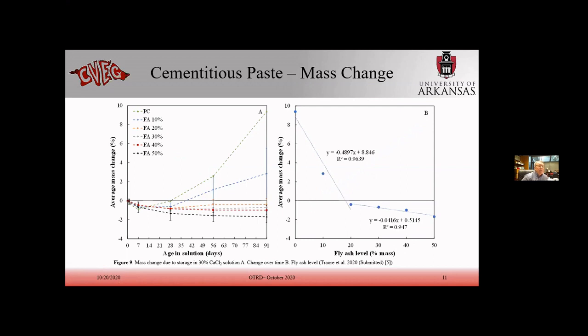Likewise, mass change. We looked at the change in mass after the 91 days in the calcium chloride solution, and this is a gain. As you store the cubes in the salt solution, 30% CaCl, it cracks, but the cracks allow more of the calcium oxychloride to grow in there. So you're not losing parts of the cube, it's swelling, so you're gaining mass.